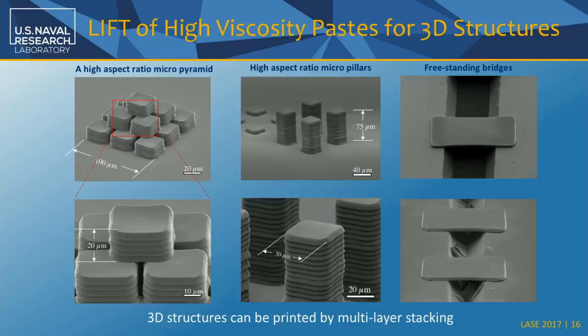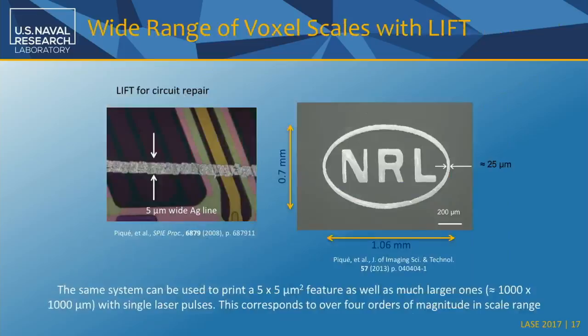Again, you notice how it was being released, and if we do that right, we can actually capture it and make bridges and also cantilevers. So to put this in perspective, another thing that we have looked at is the range of sizes of these voxels that we can print. This is an example showing 5 micron by 5 micron square voxels to an entire pattern that is of the order of a millimeter in 1 dimension. Each of the individual voxels here and this entire pattern were generated with 1 single laser pulse. So as long as we have enough energy in our laser source that we can expand the beam and then create a pattern here, we can actually print it.